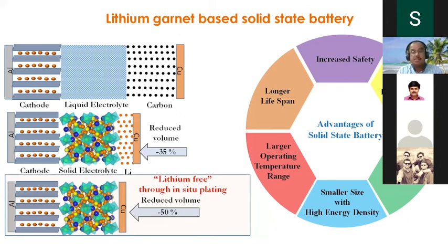So this is the biggest advantage of the solid-state battery, which helps to enable lithium metal as anode, and enables high voltage cathodes. If you combine them together, you get smaller size with high energy density. You cannot imagine anything else in the world, because lithium has the lowest reduction potential. There is a ceramic layer, and then the operating temperature range: don't think nothing will happen even if you go to 200 degrees Celsius. At 180 metallic lithium melts, so at 150, 160, it's nothing but a solid.